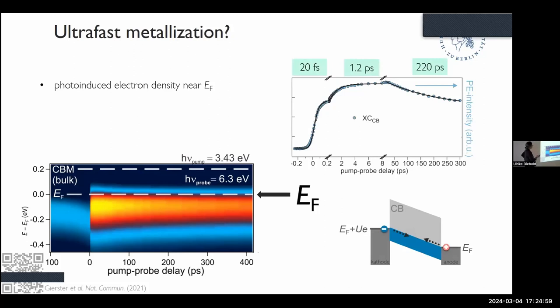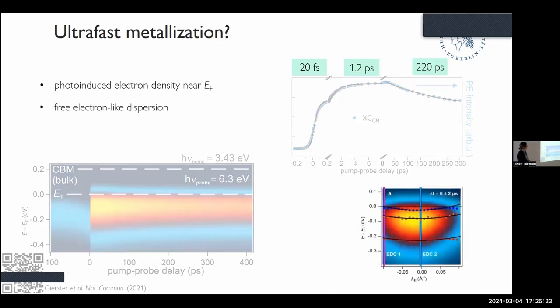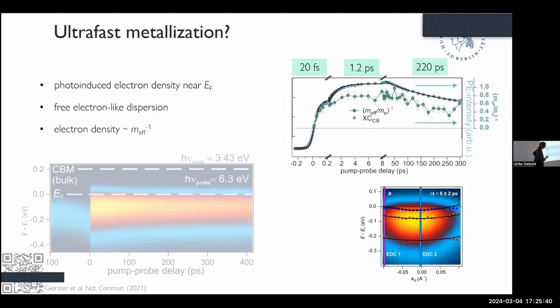Then we can look at the photoelectron intensity as a function of time. And we can monitor three different time constants, two rise times, ultra short, and then a decay time of 220 picoseconds. So it decays also on ultra fast timescales. And at the same time, we can then look at the dispersion of the electron distribution and take the inverse effective mass as a measure for the degree of localization. So this is plotted here in the light blue markers. I hope you can see that it shows qualitatively the same dynamics as the electron density.